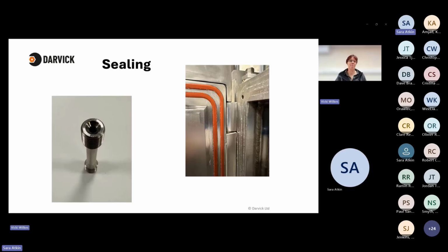So if you look here, we have hollow sample. We do hollow sample testing at the moment, and it's relatively straightforward. Basically, it's a cone type assembly. The beauty of the cone, which is to our design, is that we can vary the size of the samples, so you don't just have to have one fixed interface. You can have different diameters if you want.